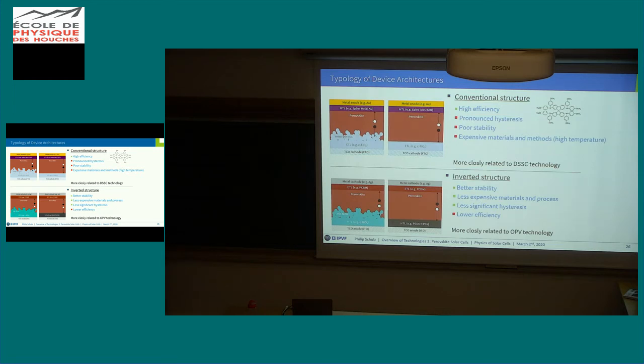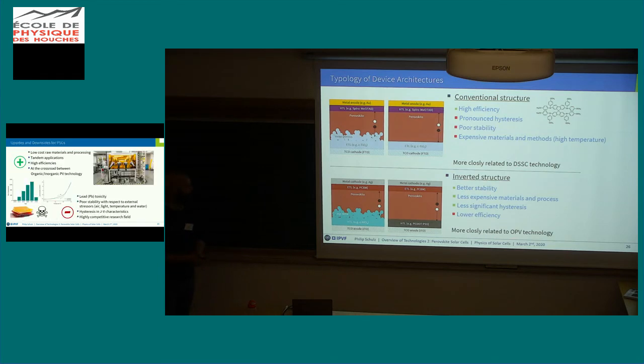The inverted structure, so this is PIN. The inverted structure, which is PIN, showed a better stability, actually much less hysteresis from the get-go, but always had to fight with lower efficiencies. I think the current record is on the order between 22 and 23%, and came out earlier this year as well. And this is now a little bit more related to the classical OPV makeup of a cell.